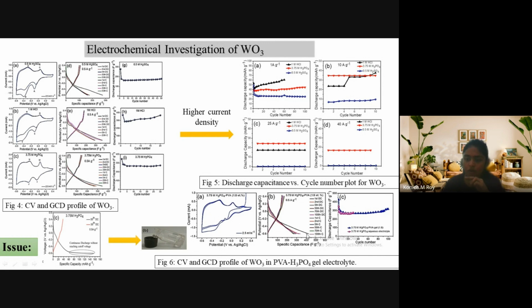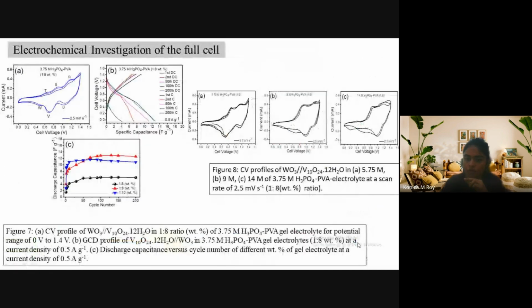So here, after optimization, we took 1:8 weight percentage of the gel electrolyte, and the CV profile is similar to that of the aqueous electrolyte, and the GCD, that is the galvanostatic charge discharge profile, matches well and supports the CV profile. And here we could see that it could run for more cycles, up to 3000 cycles, which was not possible in the aqueous electrolyte.